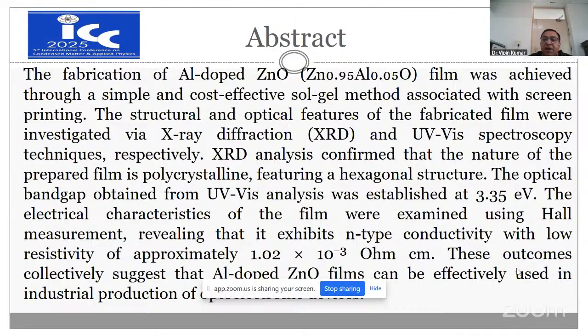XRD analysis confirmed that the film is polycrystalline, featuring a hexagonal structure. The optical bandgap was obtained from UV-visible spectroscopy. The bandgap was found to be 3.35 electron volt. The electrical characteristics of the film were examined using Hall measurement, revealing that it exhibits N-type conductivity with a low resistivity of approximately 1.02 × 10⁻³ ohm-centimeter. These outcomes collectively suggest that Al-doped ZnO films can be effectively used in industrial production for optoelectronic devices.